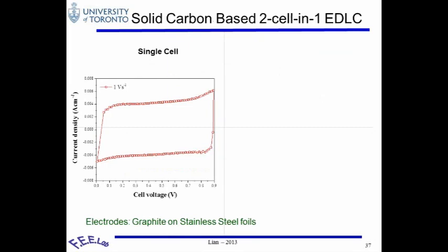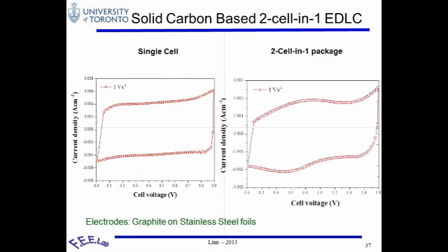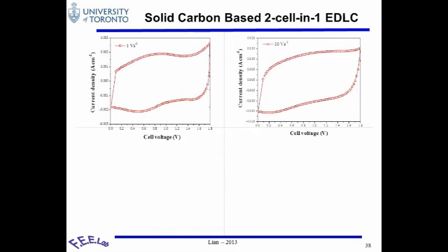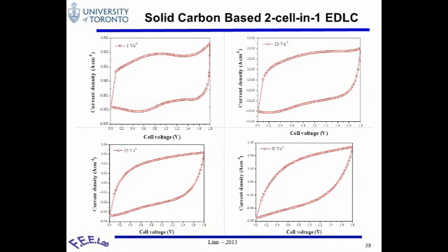So with the same kind of idea, we apply this to the graphite electrodes. This is 1 volt, one single cell here, 1 volt per second, and this one is 1.8 volts. So this is 2 cells with the same idea. We stack them together, and then we can go from 1 to 10 to 25 to about 50. It gets a little bit tilted.